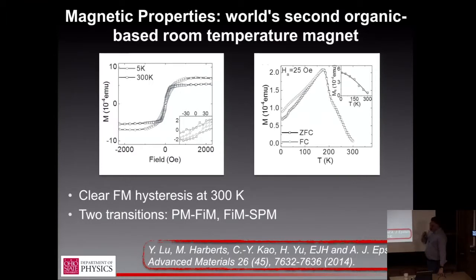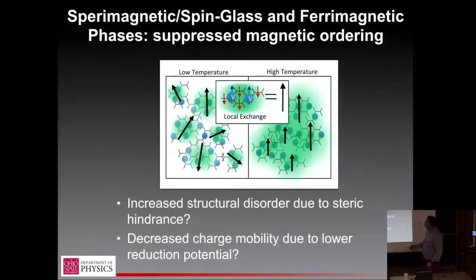And so this is pretty weird, right? Most ferromagnets get worse as you make them hotter. But not only does the magnetization increase, but that hysteresis loop I showed you at 300K, which is nice and sharp, gets very squishy and sort of banana-like as you go to low temperature.